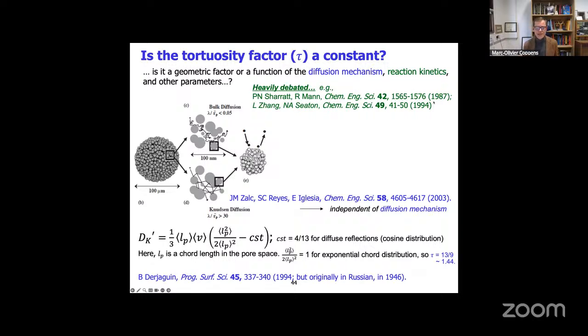Already in the 1980s, there were models including diffusion and reaction, and where they said, well, reaction kinetics may play a role actually in this tortuosity. So that already shows you it's not just a geometrical factor. Then it was debated whether diffusion mechanism plays a role. What Zalc, Reyes, and Iglesia showed through their kinetic Monte Carlo simulation, that luckily it's independent of whether you have Knudsen or molecular diffusion. However, their model did not include the roughness that I actually demonstrated to you plays an important role. So one has to be careful.